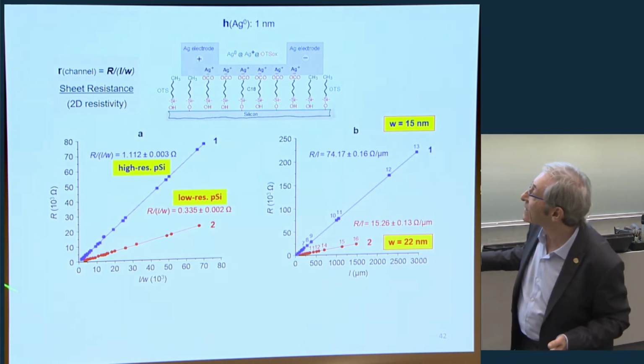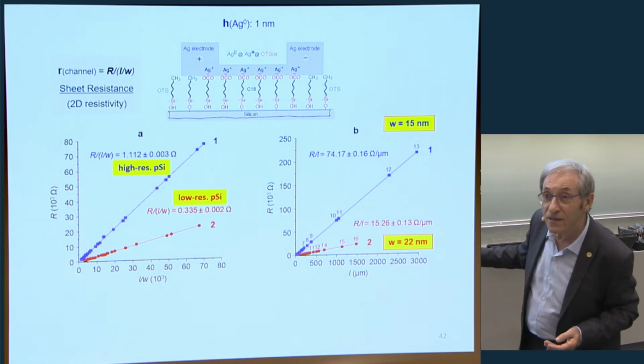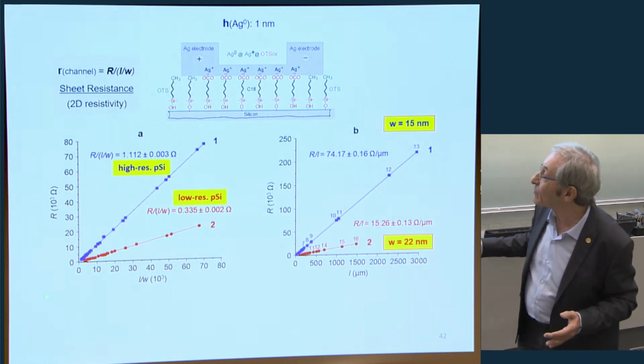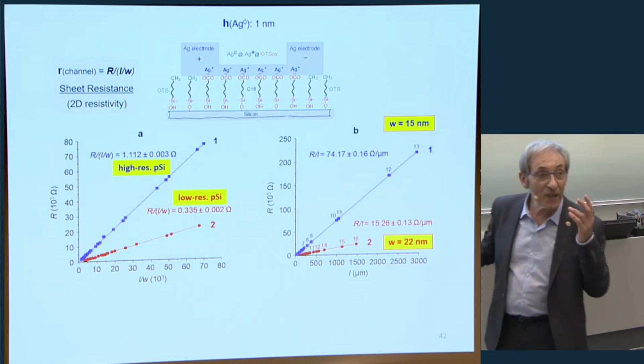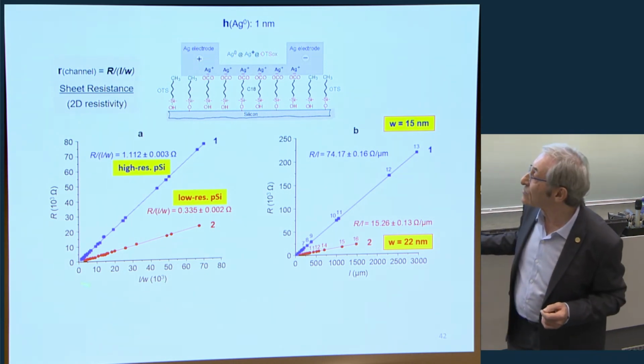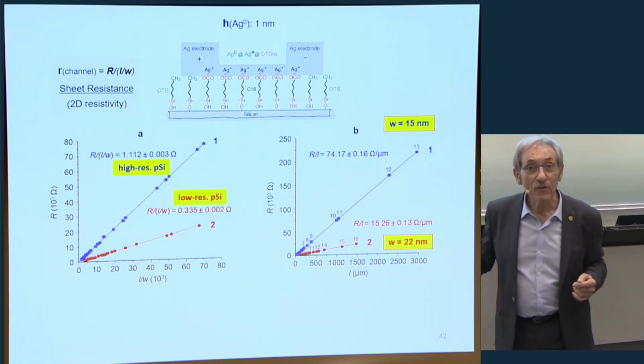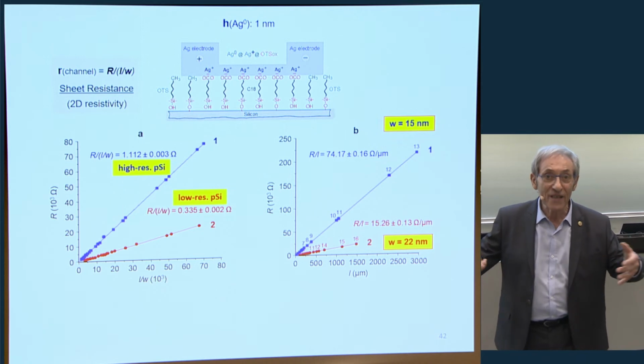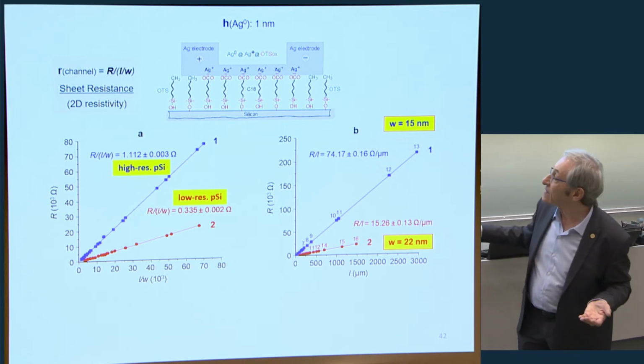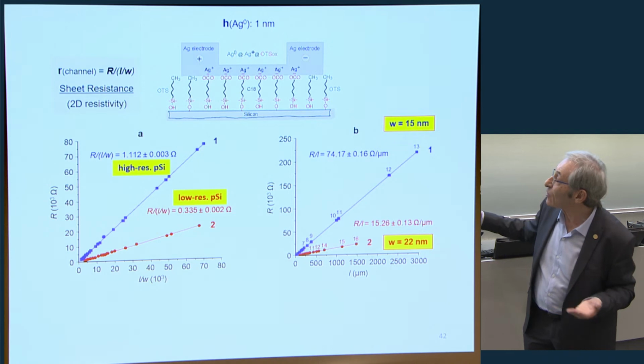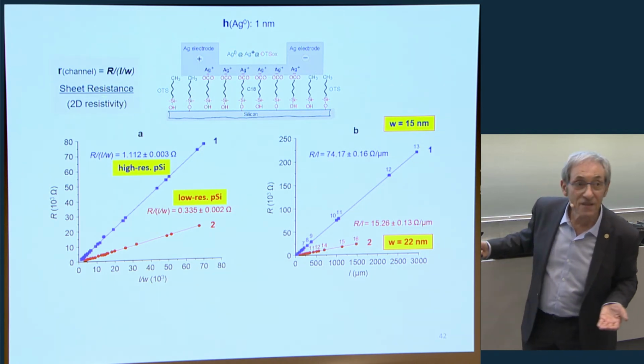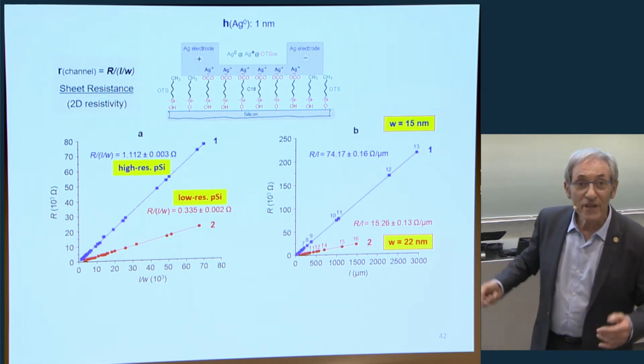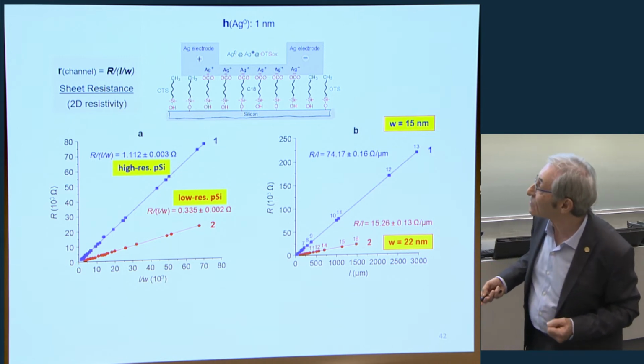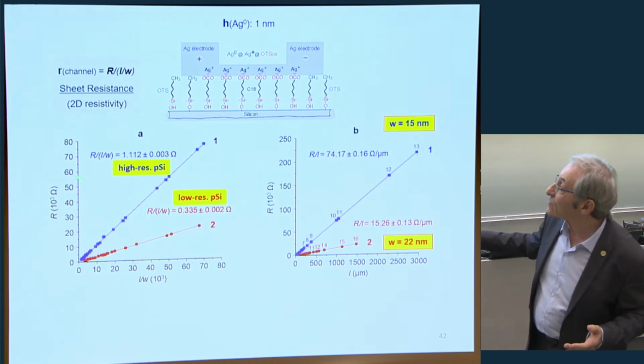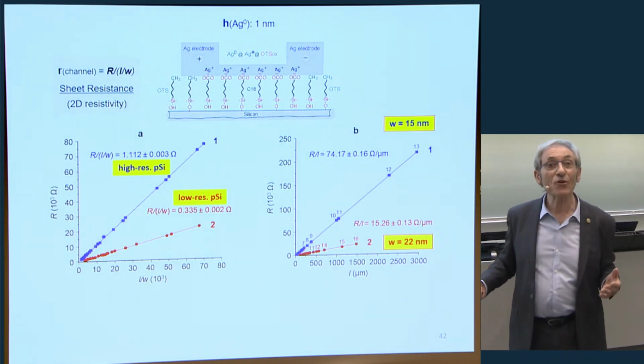And here you see that we have the resistance. We just measure the resistance by applying a voltage of 1 millivolt versus the length of the wire divided by the width. So this is resistance normalized by the length and the width. And the result, from the slope, is what is called sheet resistance. But this gives you a measure of how good these conductors are. Now, you see 2 curves here. And now is the next surprise.